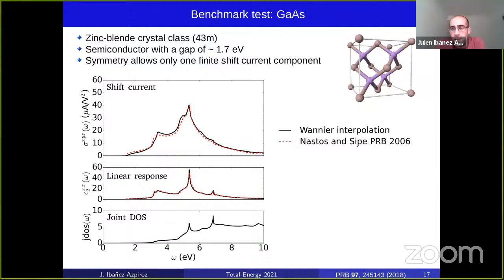It could be a similar meaning. As said, both the linear and the shift current response show the same peak structure, and the origin is actually the joint density of states. Where two bands are connected at that energy and have more or less parallel dispersion, you will have a big peak in the joint density of states, and this will also be shown in the shift current.